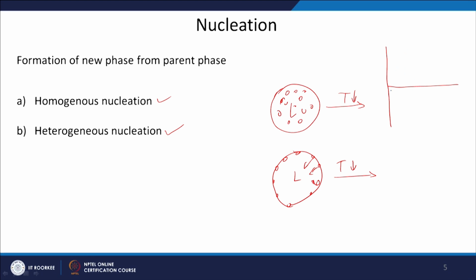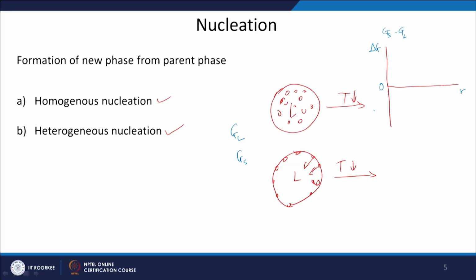Suppose you have two axes here: the y axis is the delta G axis, and the x axis is the radius of the nuclei. Suppose my liquid is not the stable phase, so my system wants to go into the solid phase. There is a free energy of the liquid phase, and a free energy of the solid phase. Delta G will be equal to Gs minus Gl. This is the change in free energy. And if you remember, we said earlier that the transformation will take place only when the free energy change is negative. At this point it is 0, and the transformation will take place when the free energy is negative.